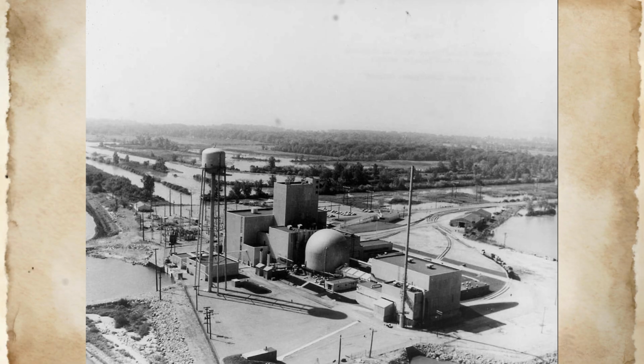The first breakthrough in the forensic investigation occurred during systematic examination of the reactor's inlet plenum region beneath the core support structure, where investigators detected a foreign object that did not correspond to any component shown in the reactor's design documentation. The object's location, size, and geometric characteristics were consistent with a deflector plate that had broken loose from its original mounting position, providing the first direct physical evidence of the mechanism that had caused the fuel damage.